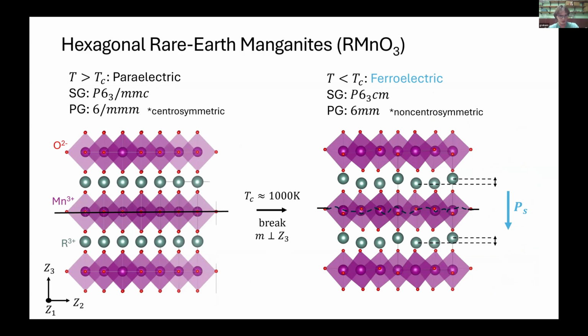So at room temperature, below 1000 Kelvin, you cool down from this 6/mmm phase. You break the mirror plane perpendicular to the z axis, and the displacement of these rare earth ions gives you your ferroelectric polarization. And you have space group P6_3cm and point group 6mm.